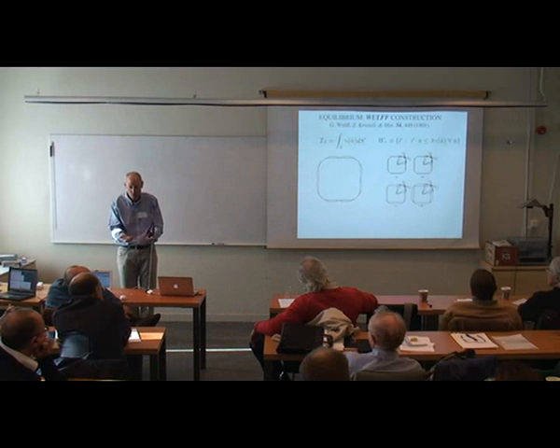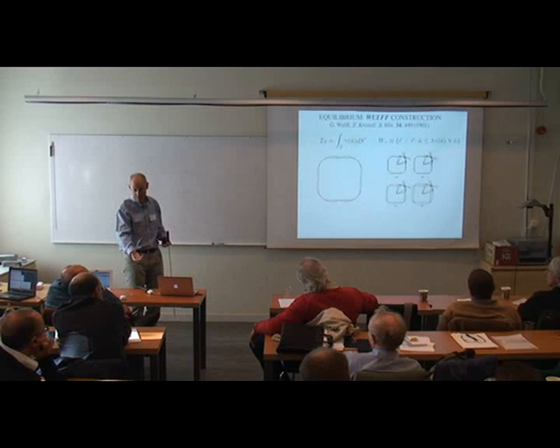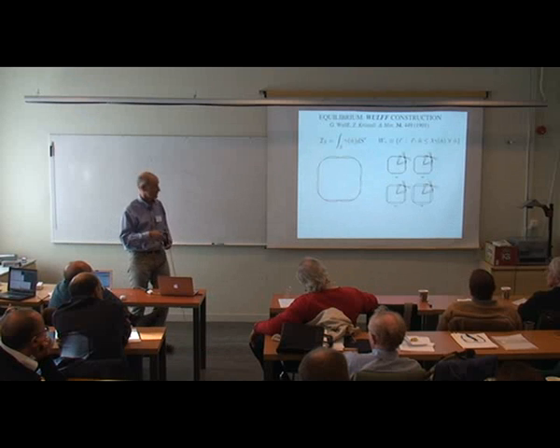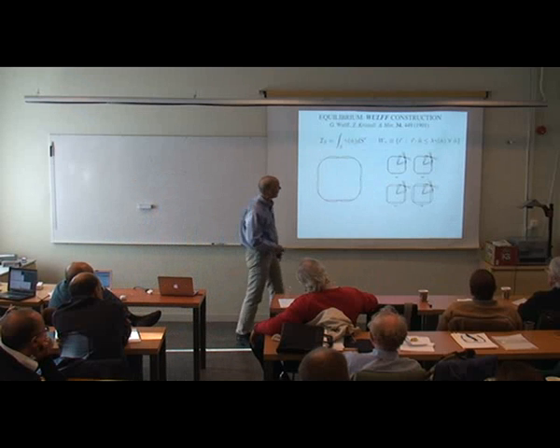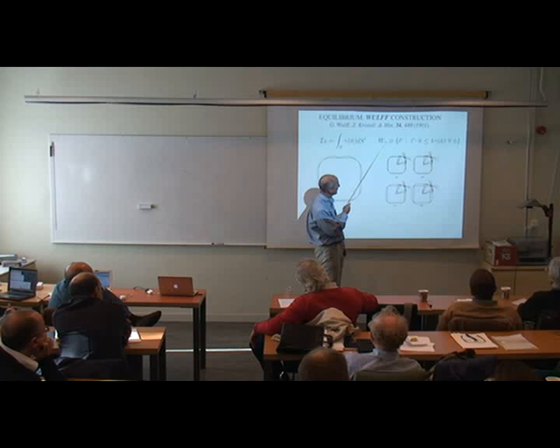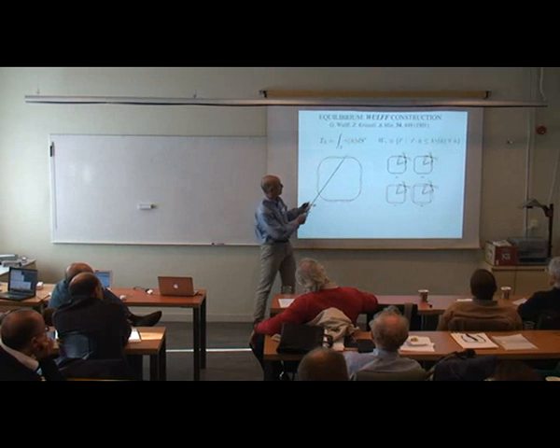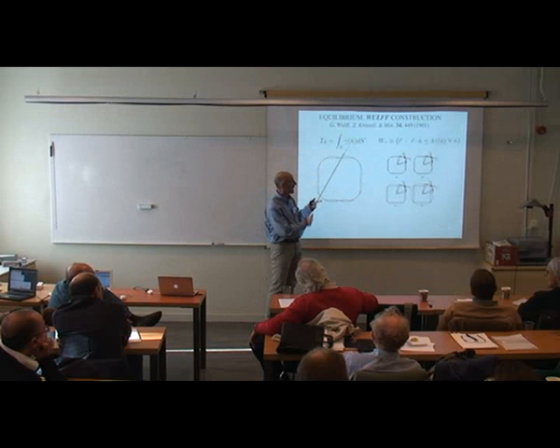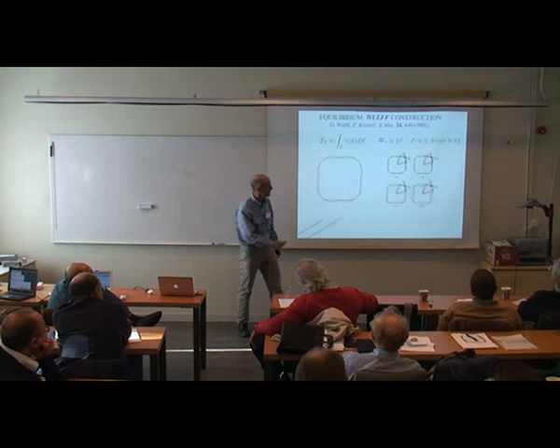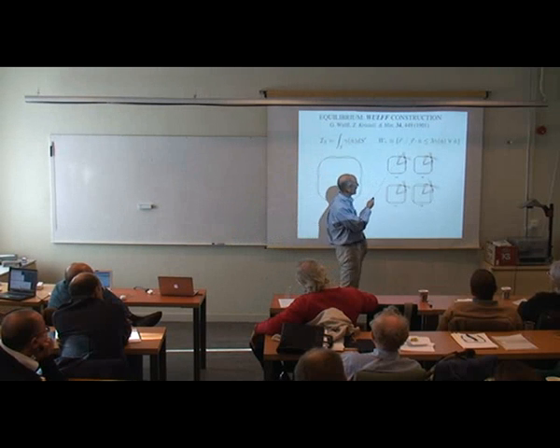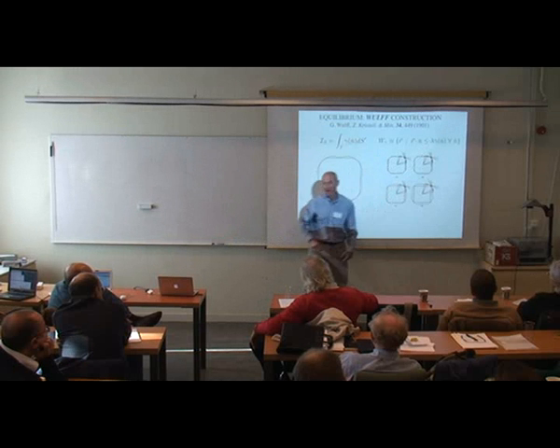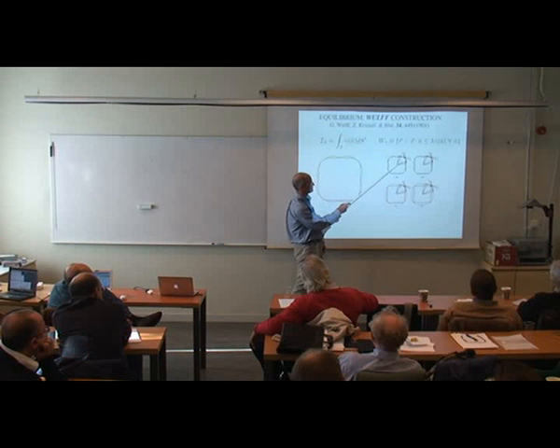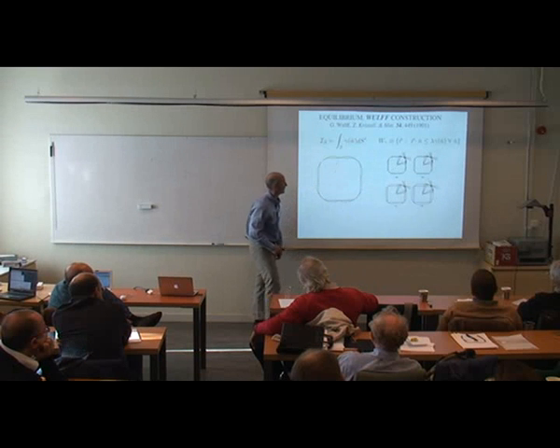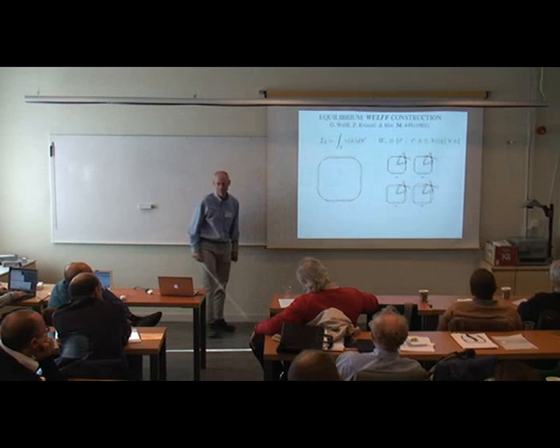So normally what people do is wait until the thing reaches equilibrium and try to invert this to get the surface energy, because you'd like to know that. So here's what the shape actually is. You want to imagine that, since God gave you the free energy, you make a polar plot of that. Then you take an inner envelope, which is just the set of all points such that the projection of a radial on the normal is bounded from above. You can see the geometry of it as I constructed it here, and that's the Wulff shape.